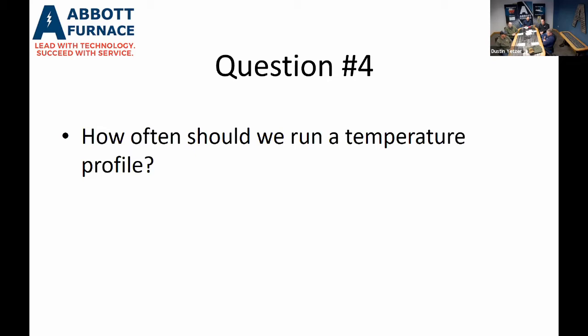Some of those codes also require a redo of that temperature profile after a large rebuild, if the furnace was taken away from original design parameters. Often if you're increasing the amount of power in one zone, that could affect what the parts see, so they ask that be done. Now, it's never a bad idea to do them more often, because what that begins to build is a historical record of changing the equipment.